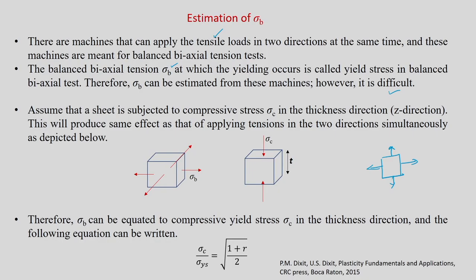So, instead of that, what can be done is, assume that the sheet is subjected to compressive stress, let us say sigma c, in the thickness direction, for example, like this. You have the same sheet element, and you are compressing it with sigma c. This will produce the same effect as applying tension in two directions simultaneously, as depicted below. Instead of pulling equally in the in-plane directions, you compress it perpendicular to the sheet. When you compress it, it will anyway expand, which is what equiaxial tension is going to do. So, then